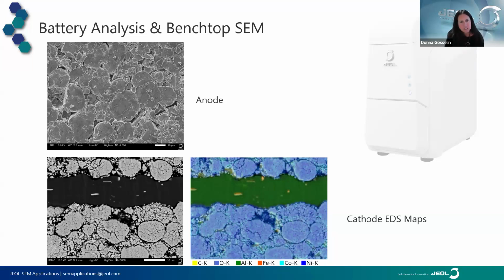And our benchtop systems can even be equipped with JEOL's EDS detector for elemental analysis. And to the right of the cathode image, we see an overlay of X-ray intensity maps on the backscatter image so that you can really see the elemental distribution across this cross-section.